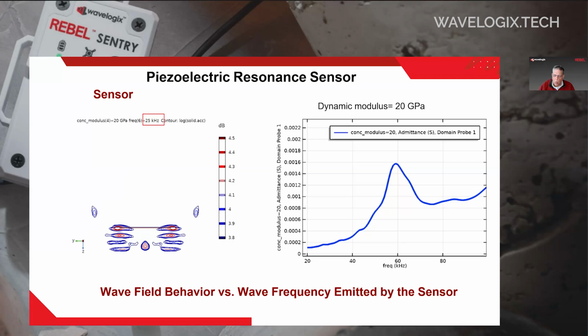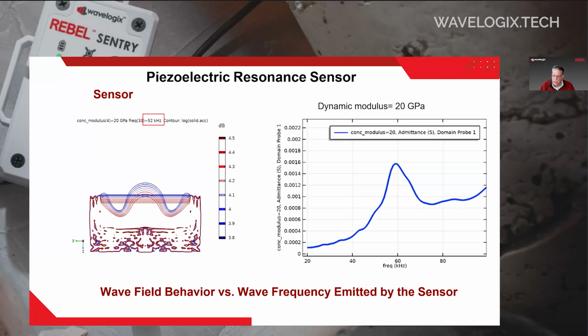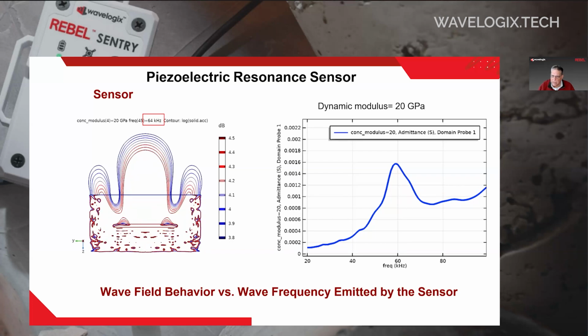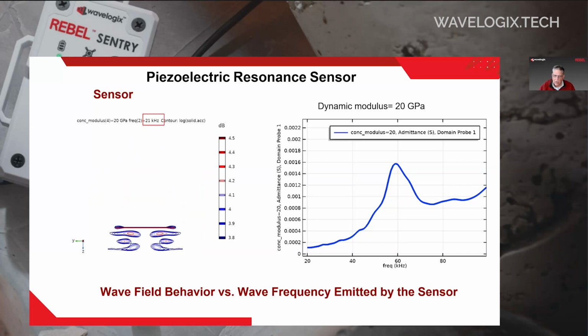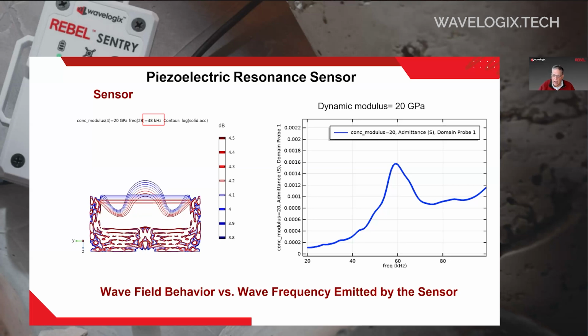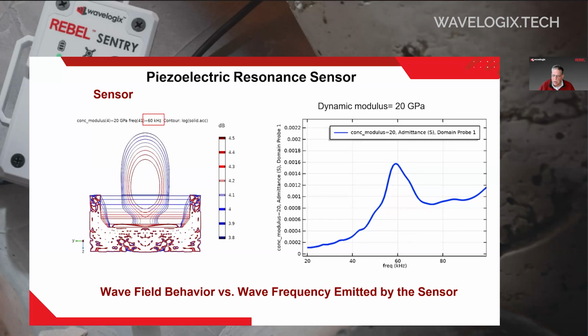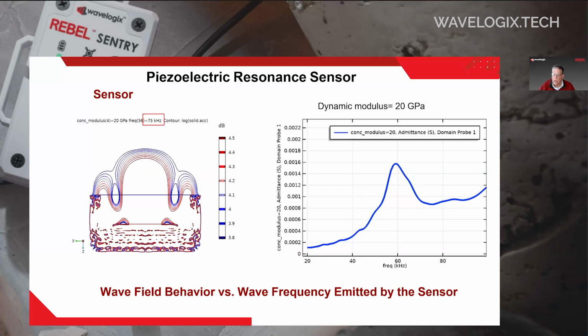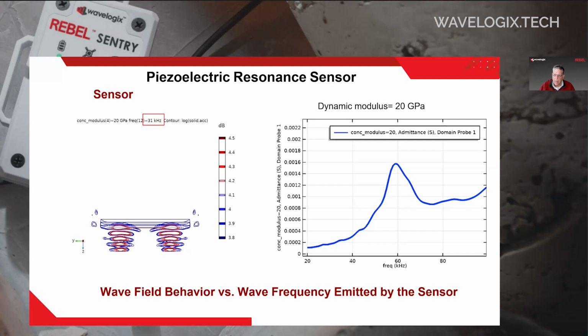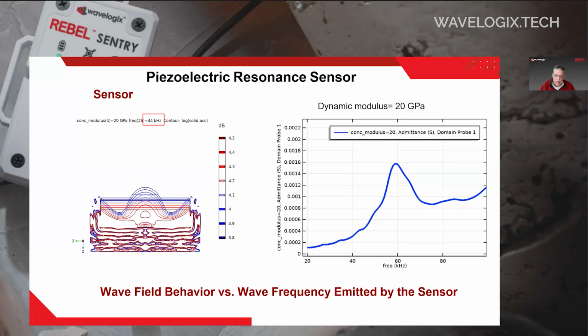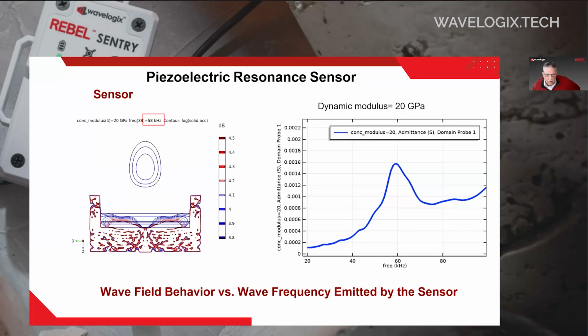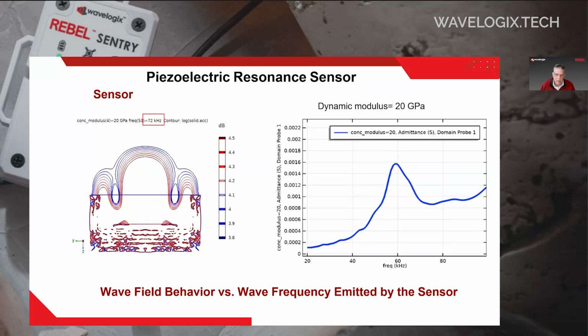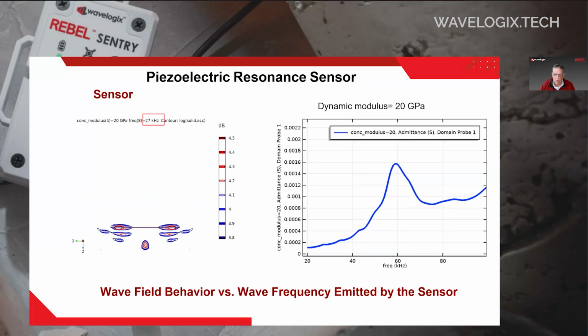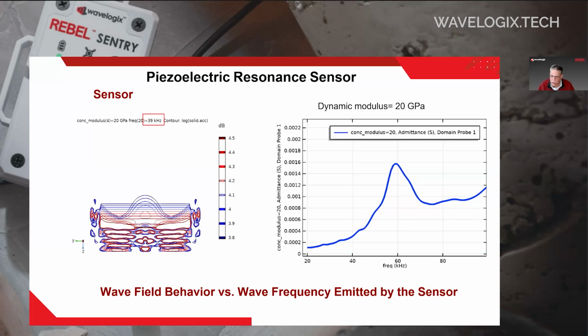And when you hit a point called resonance frequency, or the resonance of the material, and every solid material, based on its stiffness, will have a resonant frequency. You can see the chart on the right actually is measuring the different frequencies at a different resistance level. When you hit its lowest point of resistance, you peak, and that peak is the resonant frequency. On the left-hand side of the chart, you can actually see the wave representation of that wave. When it actually hits at resonant frequency, it kind of explodes. And that's what we're looking for.